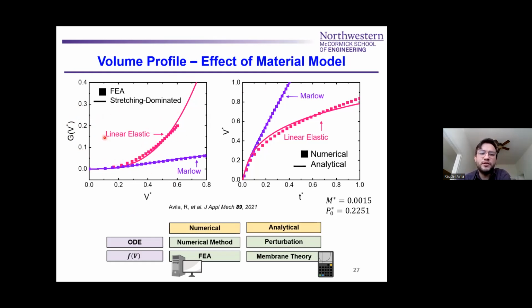If you assume that your membrane is linear elastic, you can see that at the beginning of the deformation, when the deformation is small, of course, these two agree very well. But as you increase the deformation, this linear elastic model gets significantly stiffer. So you need a large pressure to deform a set amount of volume, whereas in the real case, where you're using the experimental data in the Marlow model, that's not the case. So you need much, much smaller pressures to achieve the intended volume.